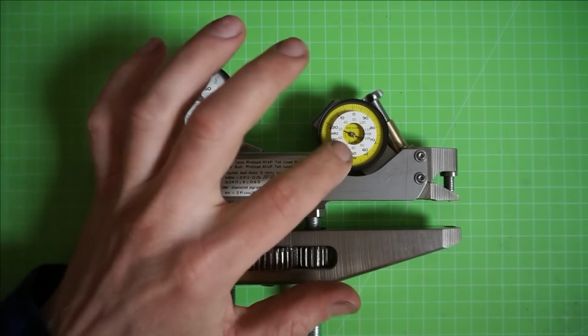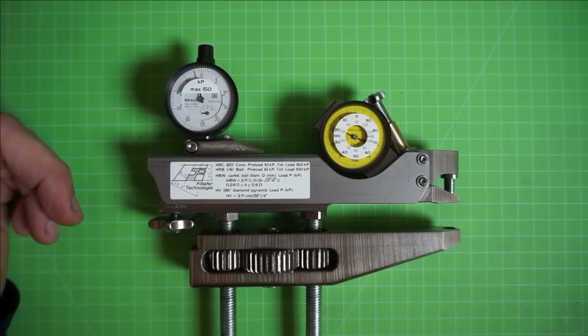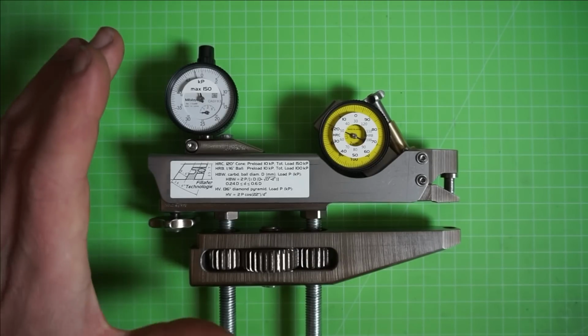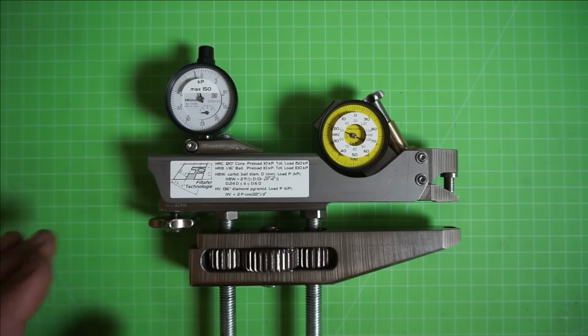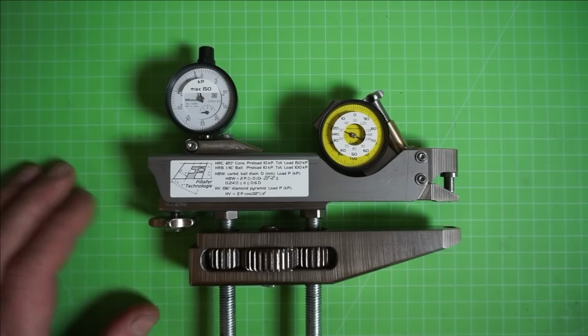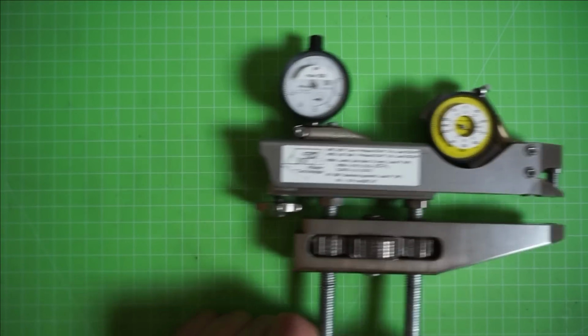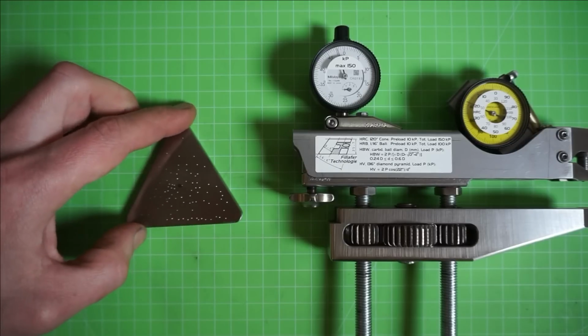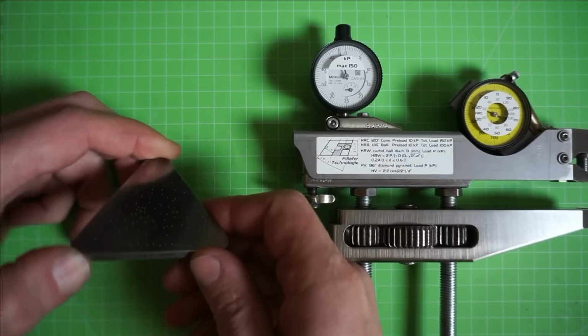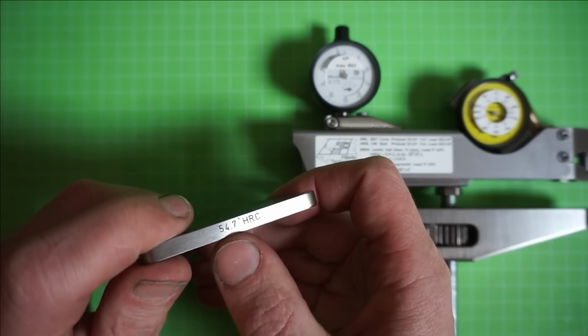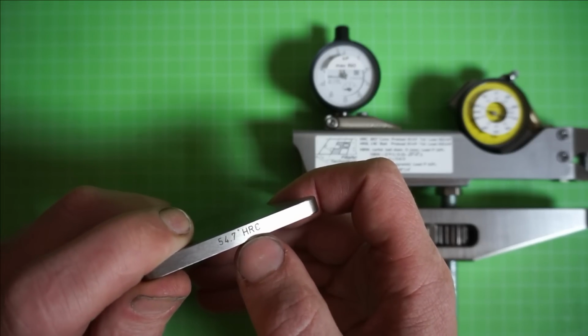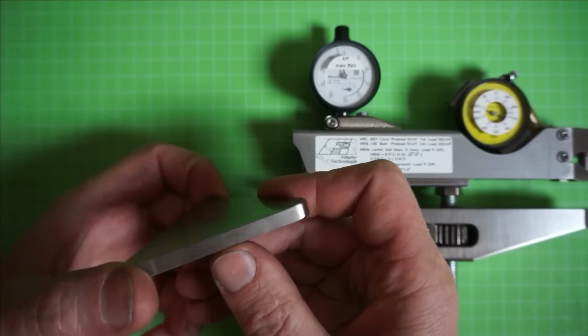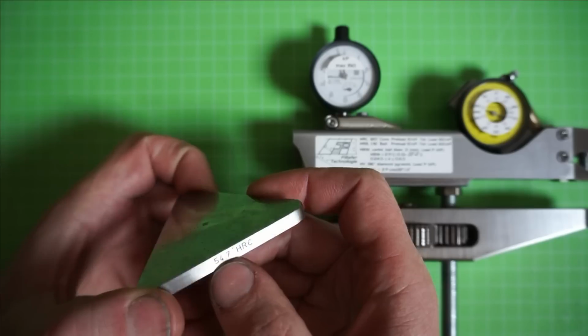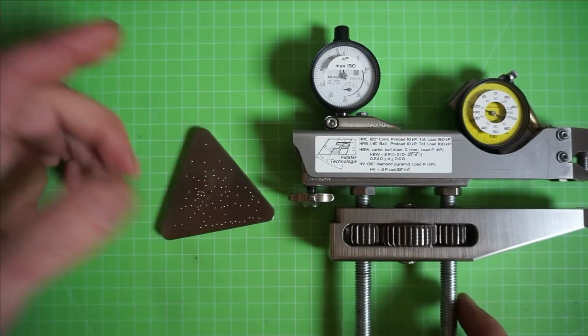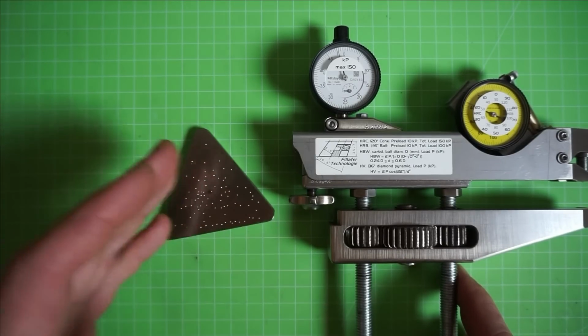Earlier I already mentioned that these dial indicators are calibrated. So what does that mean? Calibration, the word, only describes that you compare the results that you achieve with your tool with a known standard. Then you know if your results are good or not, and you also know how far away from the theoretical ideal value or ideal result you are. And in hardness testing you can achieve this with such hardness comparison plates. These you can buy. This one, for example, here is rated 54.7 HRC, that means hardness Rockwell cone. So with the Rockwell cone test method we should ideally get the result 54.7, and in reality we have plus or minus a certain error that the instrument has, that the way you conduct the experiment has, and so on.